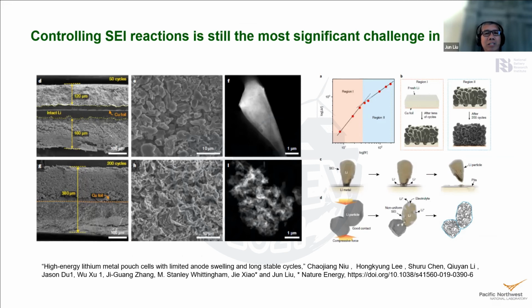We have a lot of details that I will not go through, but essentially you start with a dense lithium metal anode, and then you begin to strip and deposit lithium metal on the surface. They become granularized, become particles, and then the particles get extruded and redeposited. They become more and more porous. So what we need to do is develop new battery cell configurations, new electrolyte materials, and new surface protection methods to prevent this kind of degradation and dendrite formation on the lithium metal anode.